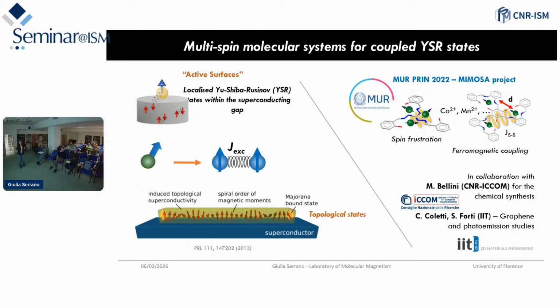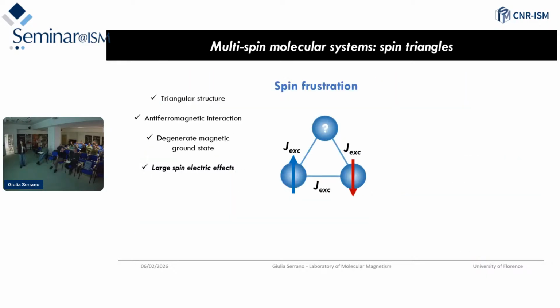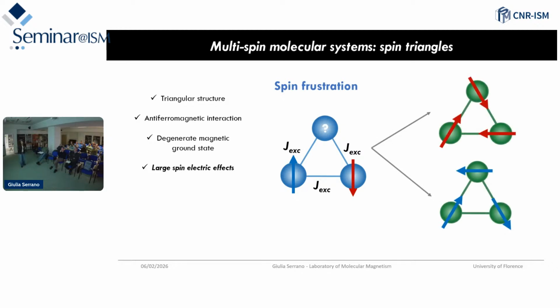the organic ligand was coupling three different ions. These kinds of molecules have a magnetism with spin frustration, meaning that each ion has an antiferromagnetic interaction with the others, but this antiferromagnetic interaction cannot be satisfied at the same moment throughout the three-spin system, and this leads to a double degeneration of the ground state that is pictured in this sketch of the spin arrangement.